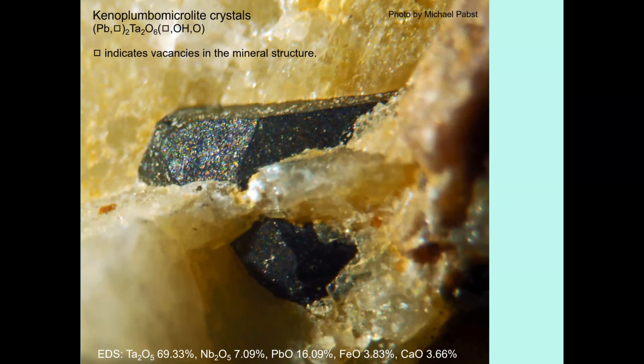But in this case, two interesting things here. First off, notice the extremely unusual formula of the Keno-plumbo-microlite. Many of you have probably not seen Keno in a mineral formula name ever before. Keno refers to those weird squares you see in the very accurate chemical composition, which comes right out of Mindat. Those reflect vacancies in the crystal structure of the mineral. And if you notice at the bottom, the EDS test results clearly show a high presence of lead in the specimens. Go to the next slide.